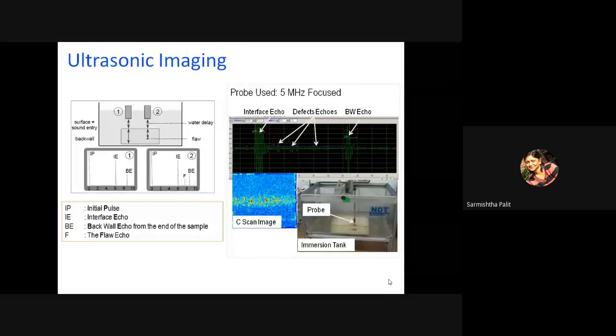Now, if I have to do the imaging, that means I cannot put this probe onto the sample. So I have to use a non-contact method, which means I need some liquid coupling. Mostly water is used, in a tank. You keep your sample immersed in the water, and the sensor can move in a raster mode, and you can get the whole signal.